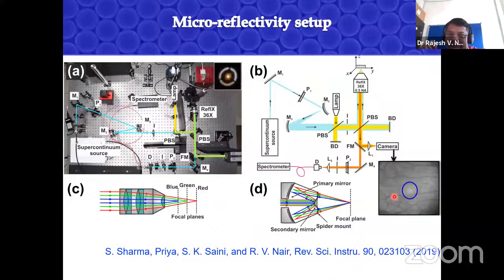So with this setup, we are able to achieve a very accurate, very precise measurement from a region which is almost free from defects. Okay, not 100%, but probably 98%. And this was a remarkable setup in the sense we can use it not only for these structures. If you have any sample a few microns in size, nanowire, 2D materials, we can easily map the reflectivity. And you can also see in the live image where the measurement is actually happening.